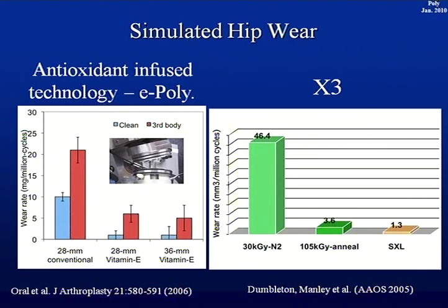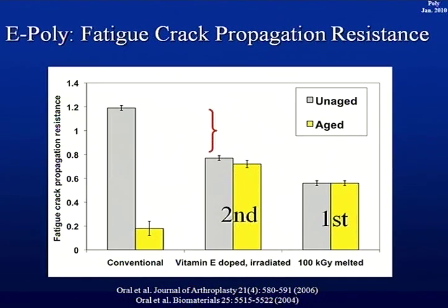It's much better than conventional and highly wear resistant, as good as the first generation remelted. And the same goes for X3, basically. You get exactly the same wear reduction by sequential annealing.